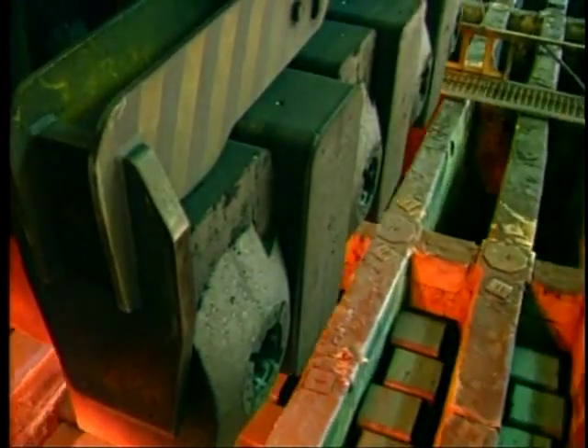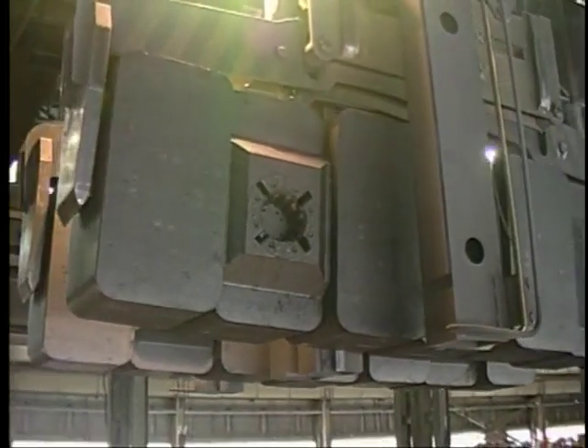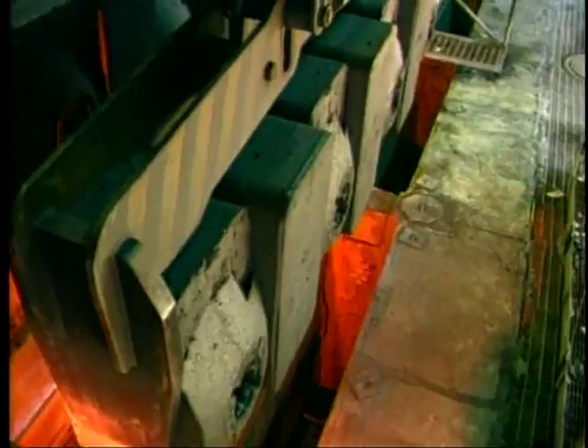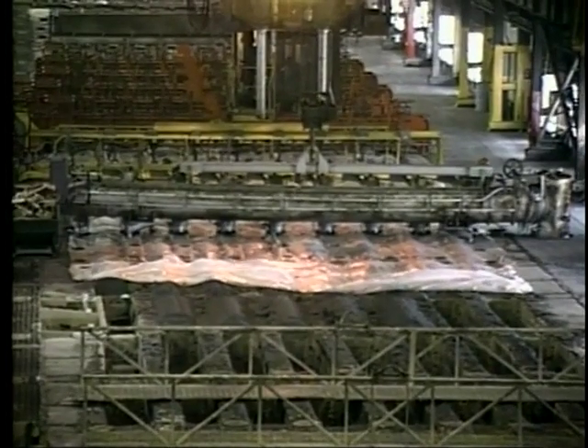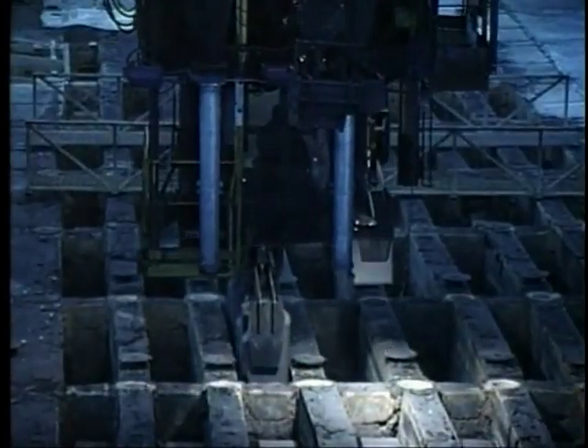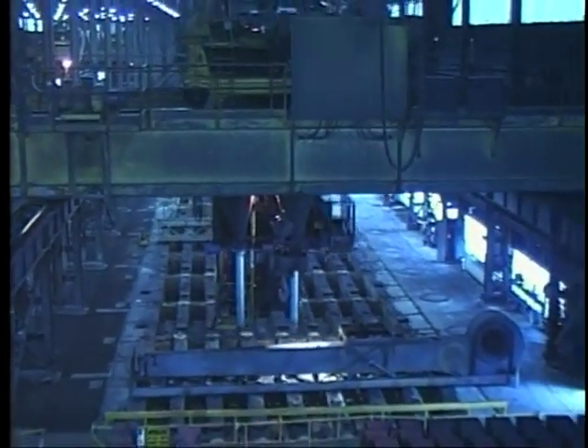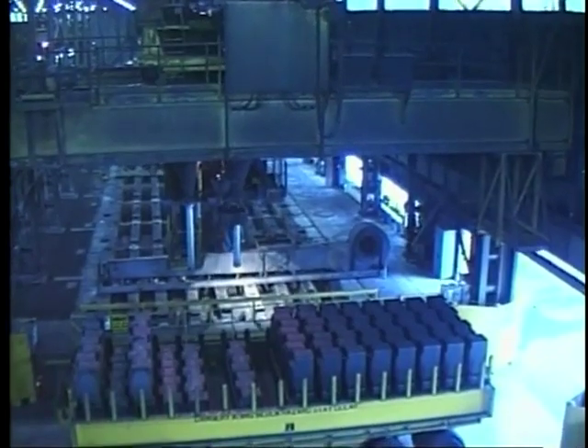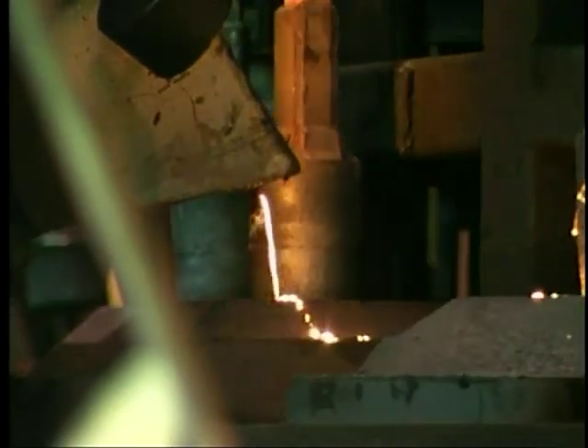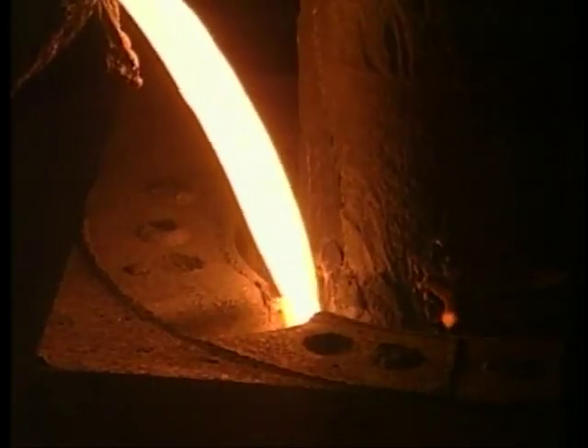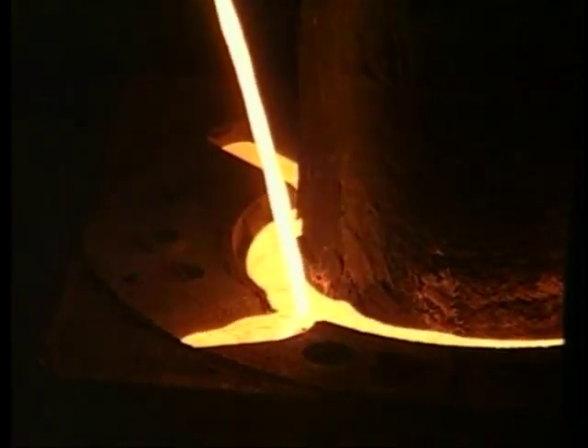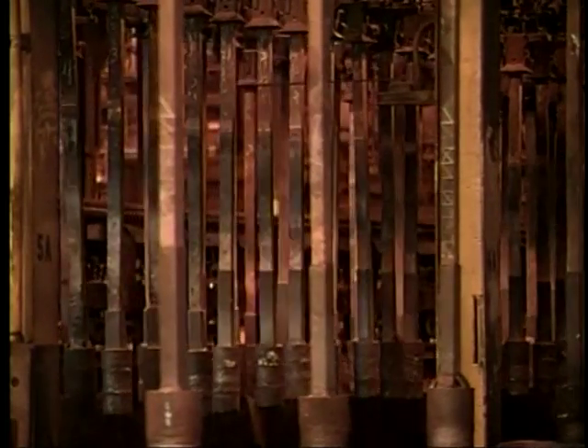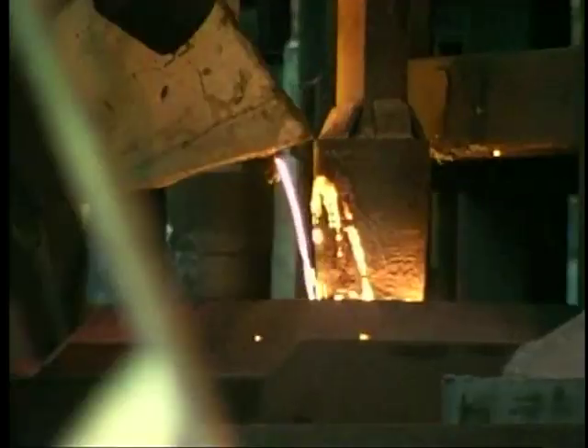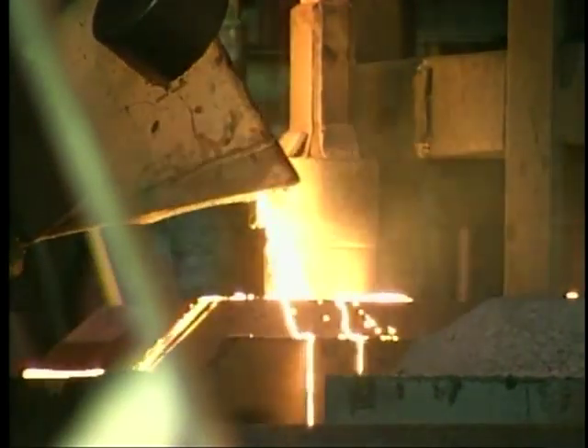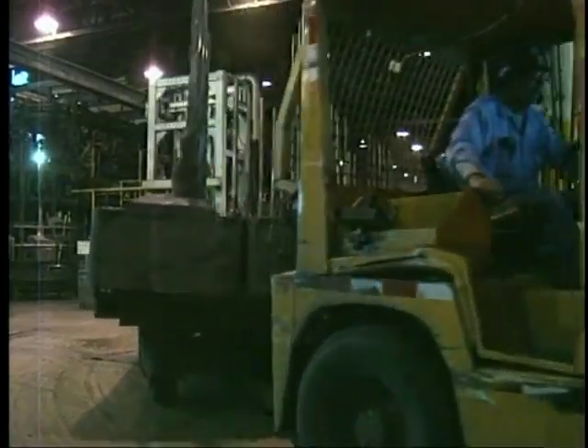Here they're placed in pits, then carefully sealed and baked at temperatures of up to 2,100 degrees Fahrenheit for about 18 days. Computer-controlled firing frames control the heating process. After the blocks are baked, they are removed from the pits, loaded onto trailers, and carried back to the central loading area to be readied for the rodding room. In the rodding room, baked carbon blocks are joined with a copper rod stub to form the finished anode assembly. Used rods are reconditioned, then carried by automated equipment to the pouring station, where they are joined with anode blocks using molten cast iron. Completed carbon anode assemblies are carried by trailer to the pot rooms.